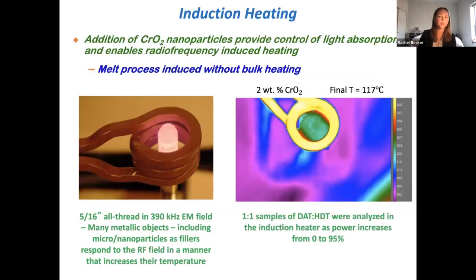So here, in order to actually use the cast molding process, there needs to be a way to melt out the printed mold from the cast. And we can do this through induction heating using the chromium oxide nanoparticles. So on the left here, we see an induction coil with a metallic screw on the inside. And as that coil is turned on, it creates an alternating magnetic field, which heats any conductive material on the inside of the coil.